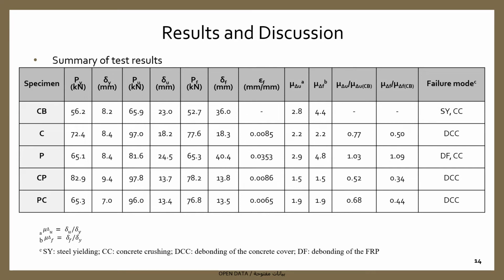Moving on to results and discussion. The results that were observed from the flexural test are shown in this table. It was clear that the ultimate load capacity of all strengthened specimens increased significantly compared to the control beam specimen. The highest ultimate load was observed by strengthening the RC beams with CP strengthening sheets. However, these multiple layers reduce the ductility significantly. It can be noticed that the P beam slightly increased both flexural strength and ductility compared to the control specimen.